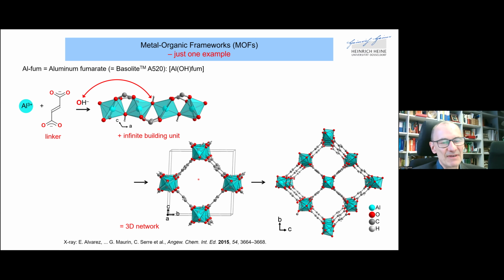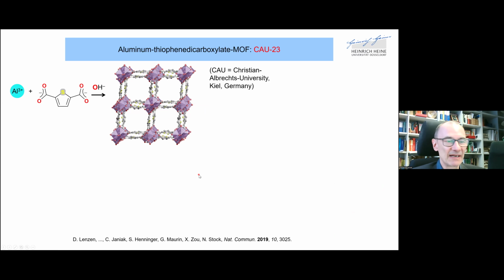And they are not maybe so common in much of the literature, but for applications, they are great because the stability of aluminum oxygen bonds is much higher than for many transition metals, maybe except for chromium and perhaps zirconium. But aluminum is certainly a very common metal. It's considered not poisonous and so on. So, and then with aluminum, you can combine a lot of similar dicarboxylate ligands, shown here as thiophene dicarboxylate, and they give you very similar three-dimensional network structures with these similar square channels.